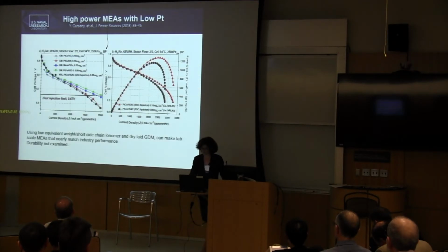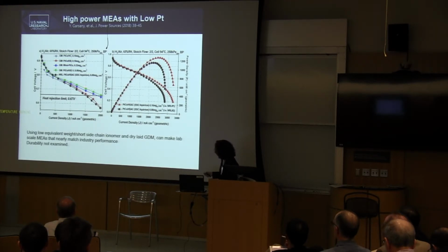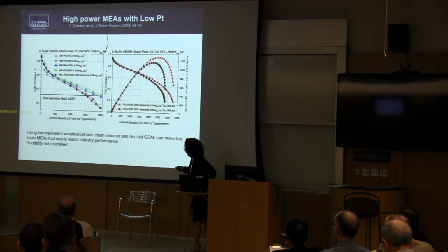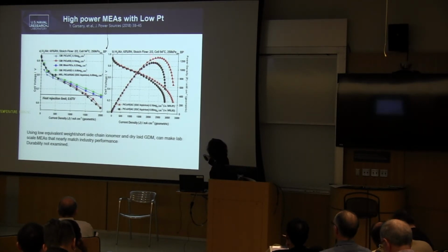And we see with this approach, we bought a commercial platinum cobalt catalyst and mixed it with the Aquivion ionomer and put it with the Freudenberg electrode. This is a very low platinum loading, and we did this in our lab, and we're just about able to meet the DOE targets. Here we are in black. On this side, this is 65% RH, so these are two different NRL electrodes. We're not quite at full power, but look at this beautiful performance.